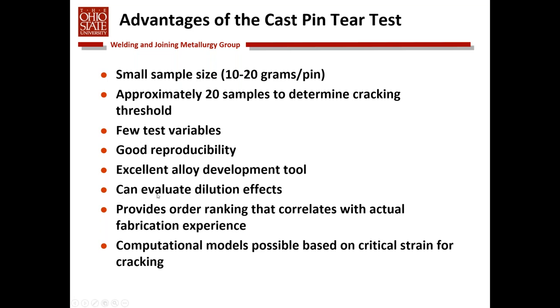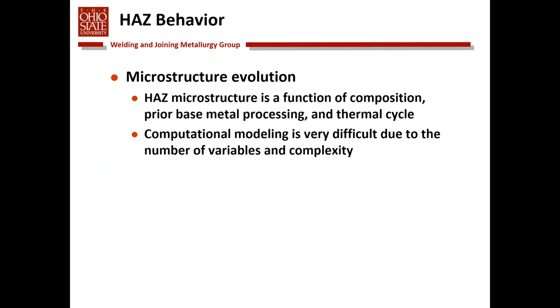The other interesting thing is you can look at dilution effects. And so if you're developing a filler metal and you know that it's going to be diluted 25% by the base metal, you can make a button that represents that particular level of dilution. We can provide order ranking that we found, at least with nickel-based filler metals, that correlate really well with fabrication experience. The other thing that the Cast pin tear test allows is computational models based on the critical strain for cracking. And so we can calculate how much strain it takes to crack a cast pin and then potentially apply that into a computational model that would relate to an actual weld.